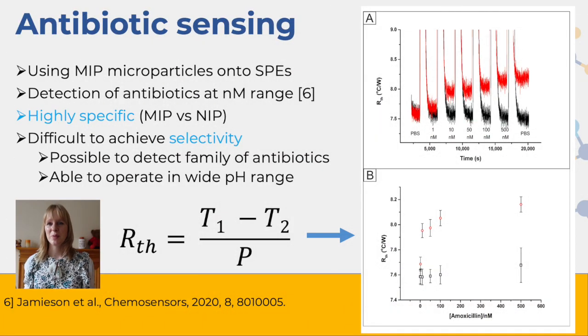The first measurements we did, we started still working with the microparticles. And the reason for that is these microparticles can really be produced in bulk. So what we did is we had this screen printed electrode, which is a piece of plastic into which we drop casted some of these polymer materials.